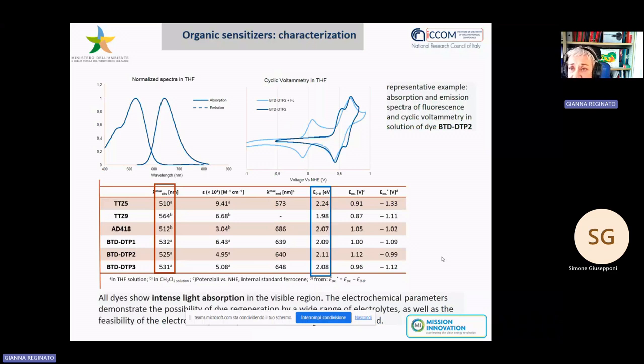Finally, the sensitizers, once they have been prepared, are characterized, as I showed you before. So we do the spectra, we do the UV-visible spectra, we do the cyclic voltammetry, both to see whether we have a good absorption of light, and if the dye can be easily regenerated by the electrolytes we are using. And I have to say that all the dyes we have prepared show an intense light absorption in the visible region and have electrochemical parameters which show that they can probably be easily regenerated. As you can see, the absorption has changed with the structure, having the best absorption, for example, with TTZ9, which also has very good regeneration parameters.